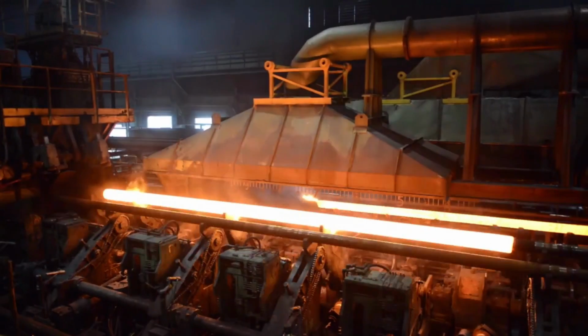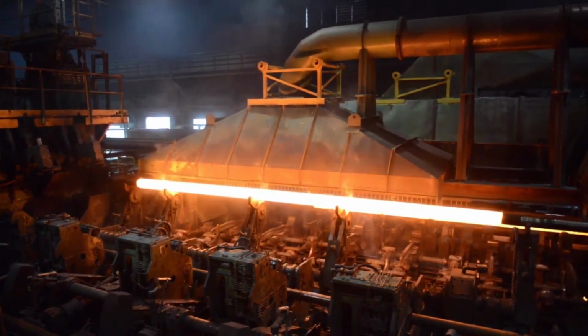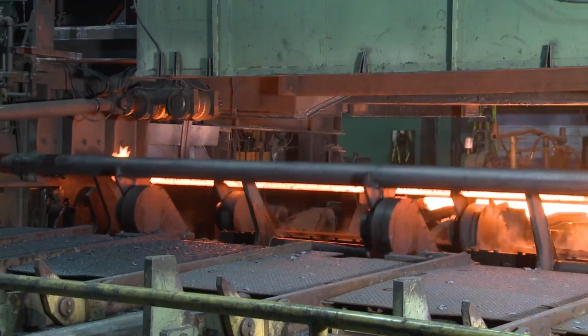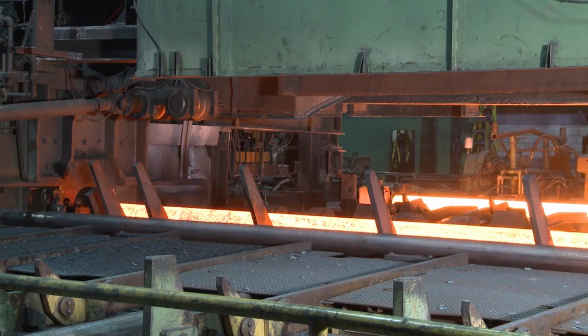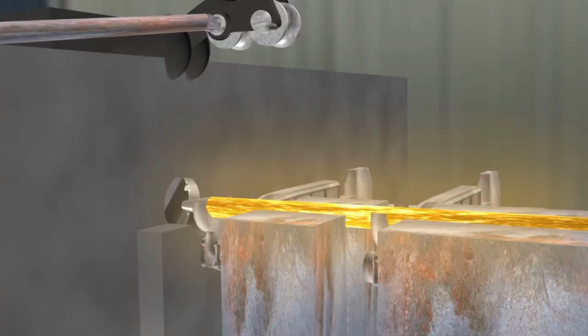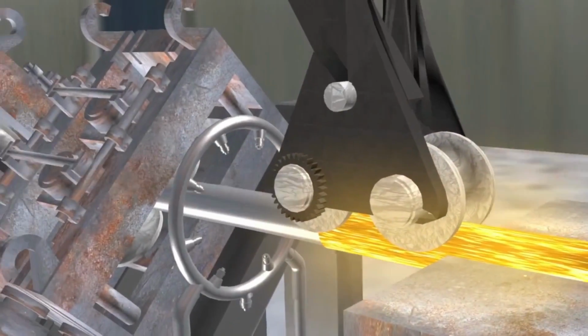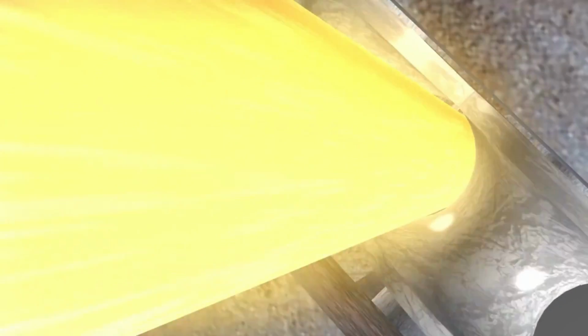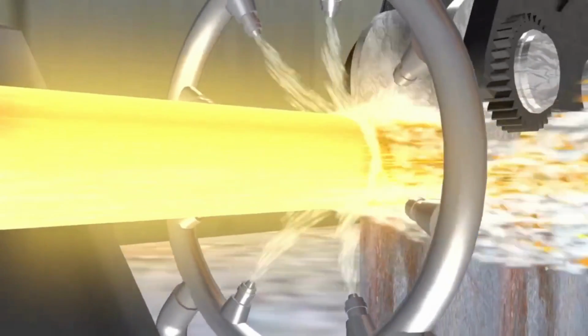The wall thickness of the hollow shell formed at the piercer is then reduced to the final tolerance by longitudinal extrusion on the retained mandrel mill. The outside diameter is rolled down by a chrome-plated tool steel mandrel by a series of 7 reduction stands. The reduction in diameter on the mandrel converts the heavy wall thickness of the piercer hollow into length as it passes through the retained mandrel mill.